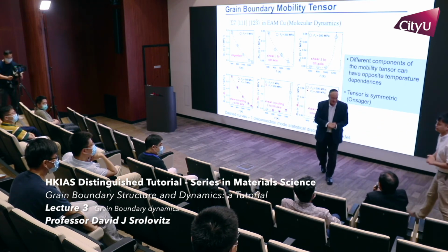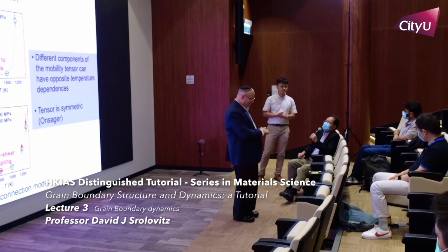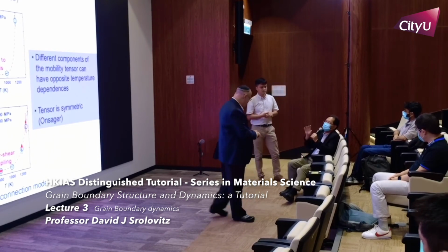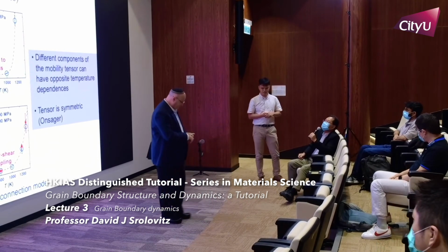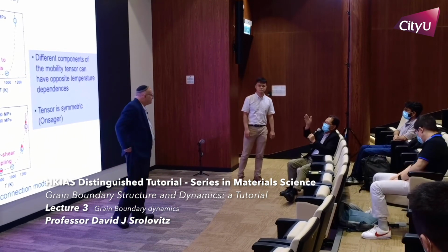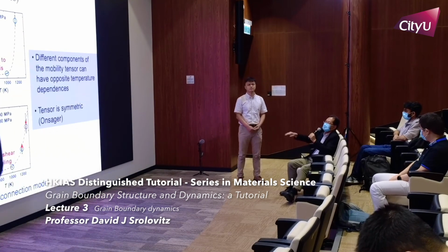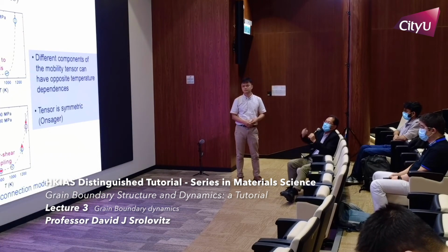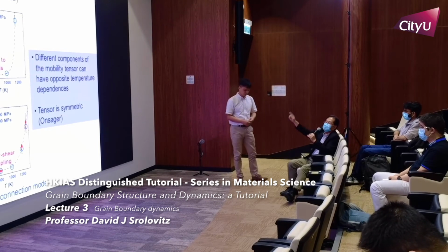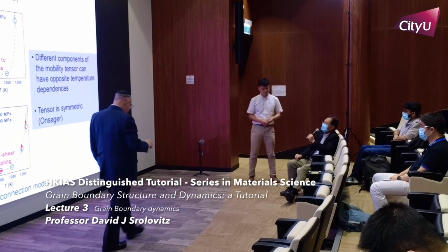Dave, I was doing a lot of superplasticity work, where grain boundary sliding contributes the highest share of the superplastic strain. At that time, we usually used EBSD to construct the probability as a function of the misorientation angle, to get the probability for different sigma 3, sigma 5, sigma 7.